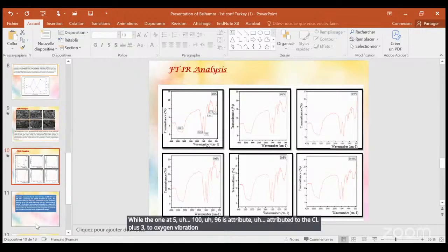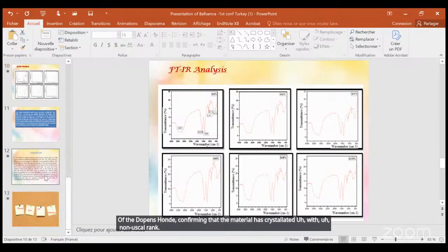Upon doping Co3O4 with Sn, a slight shift in the wave number value was observed, indicating successful incorporation of the dopant, confirming that the material has crystallized at the nanoscale.